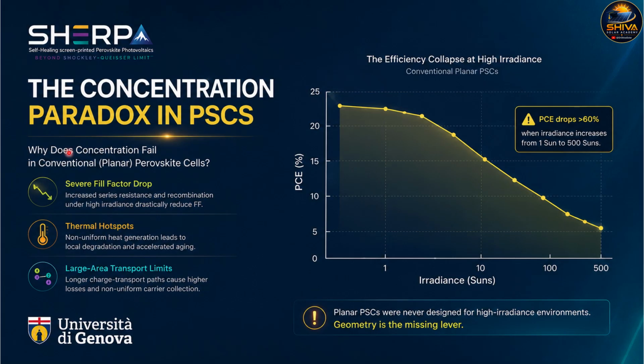Here we see the core industrial problem with conventional planar perovskite solar cells. As the light intensity increases, the efficiency rapidly collapses. As you can see from this diagram, this graph clearly shows the dramatic PCE drop under high irradiance conditions. This happens because several physical limitations start to dominate simultaneously.